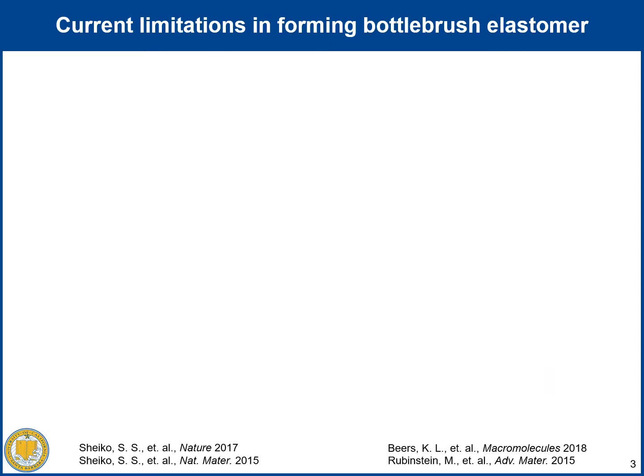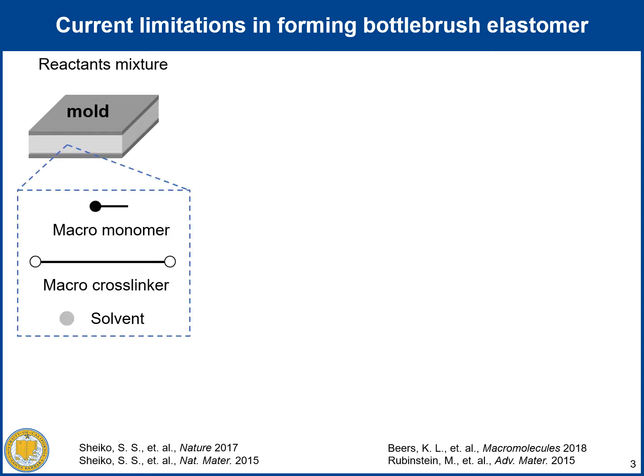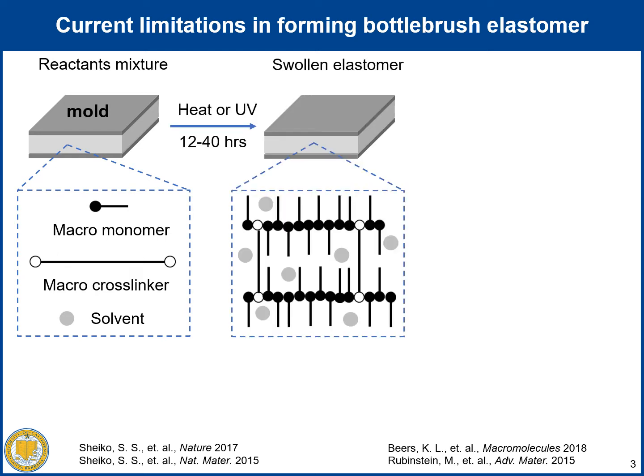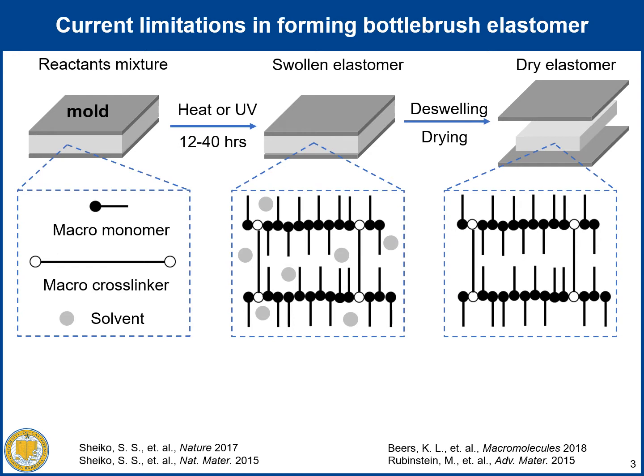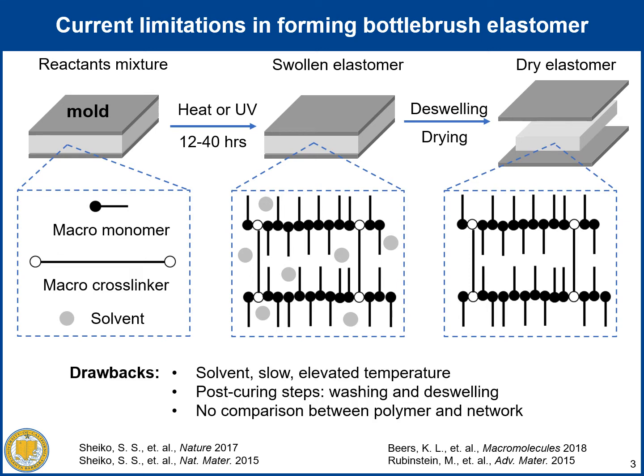But how to make the bottlebrush network? Current approaches involve processing by simple and slow molding that dramatically limits their utility. As shown, a mixture of macromonomer, macro-crosslinker, and solvent is sandwiched between two plates and slowly reacted to form the swollen bottlebrush network by heat or UV exposure. So post-curing steps such as deswelling and drying are also required to form the dry network. Also, because the elastomer is formed directly from monomers, there's no direct comparison between the polymer and the final network.